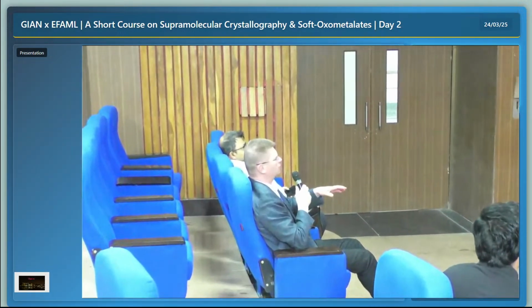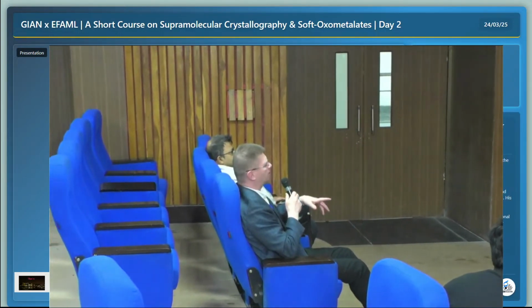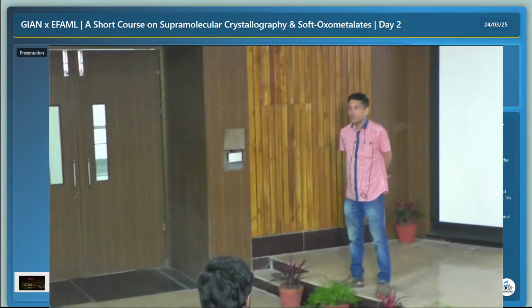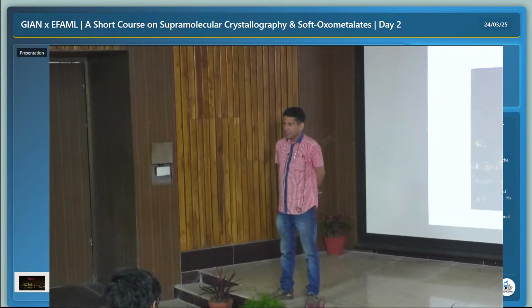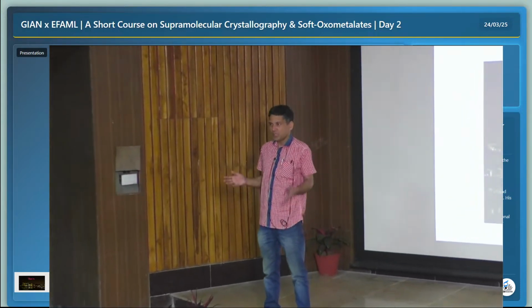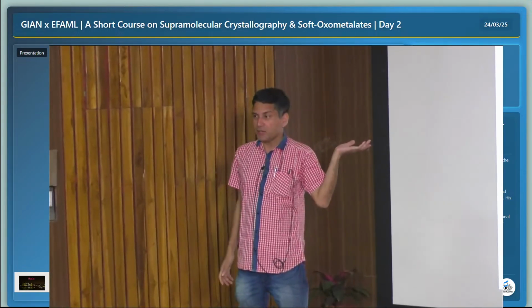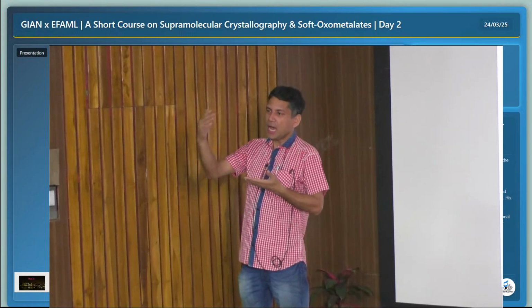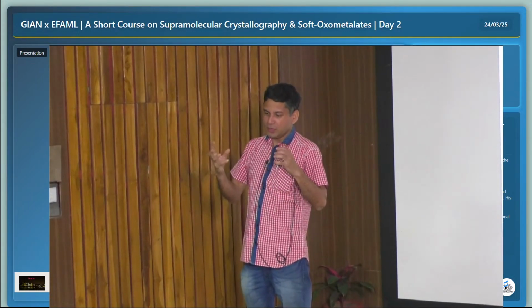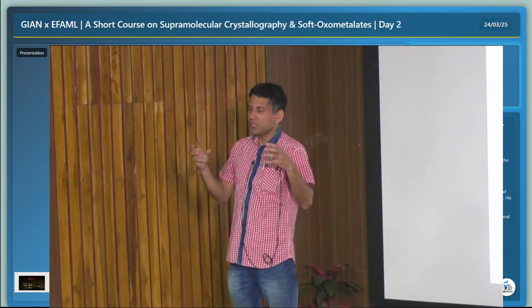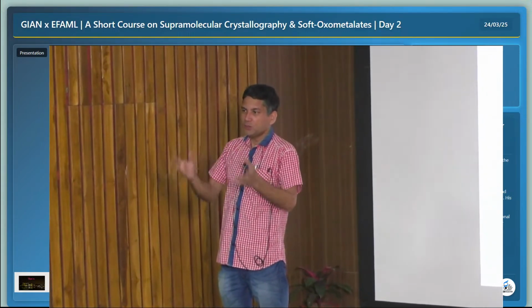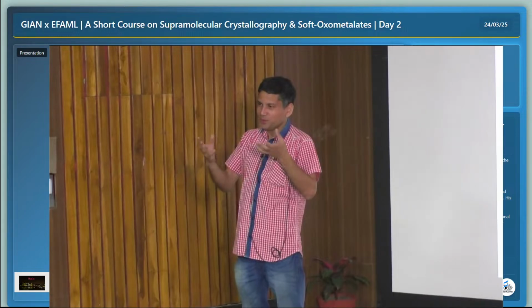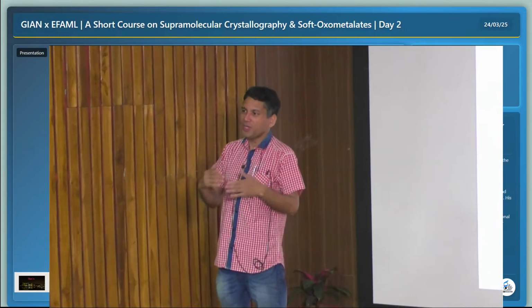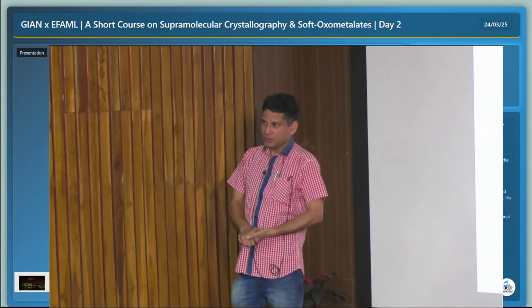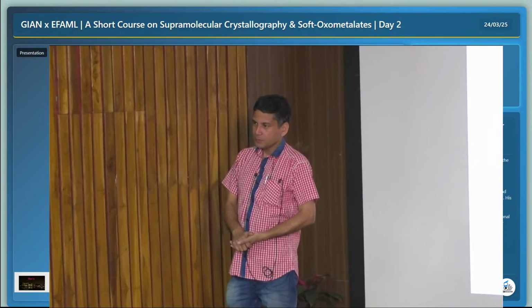Very nice gel work. So, what is the concentration you have to use in order for the gelation? Generally, if we report for only gelation, it is 2 milligram per ml, which is very, very less. Even for some gelators, it is 1 milligram per ml. But for this kind of reaction within gel, we have to use a higher percentage of gelator. Otherwise, though we claim that we are using UV light and we are using fans, so it is not heating, even UV light heats your gelator, some temperature increases and the gel may melt. So that's why we use a higher gelator concentration, you need a stronger gel for that. Very nice work. Thanks a lot.